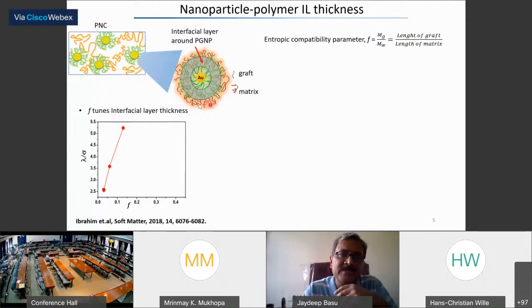And normally for good dispersion, you want to remove the enthalpic effect. That means if you don't have any enthalpic interaction, then you can prevent the aggregation and stuff like that, or minimize it. But what people realized is that one way of doing this is by putting the same polymer here as you have in the matrix, and so the enthalpic effect goes away. But there is something called entropic effect, because this polymer surface here and the configuration is different from what is there in the matrix, and that leads to very interesting behavior.